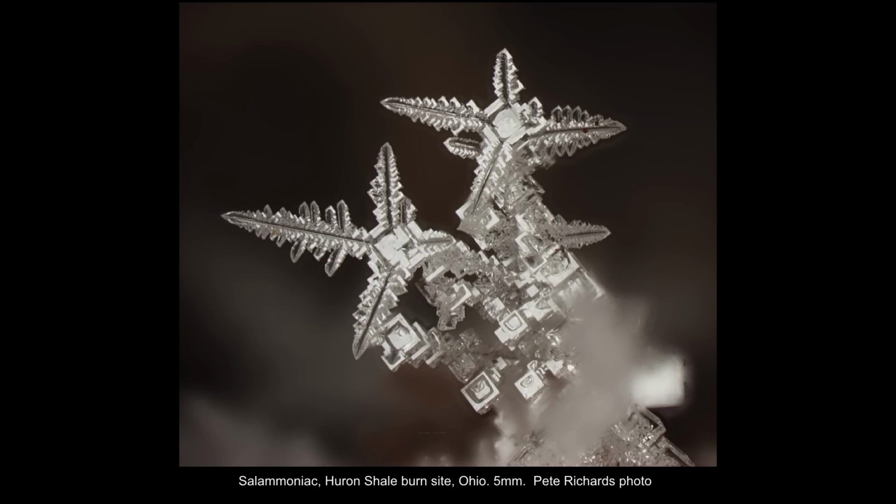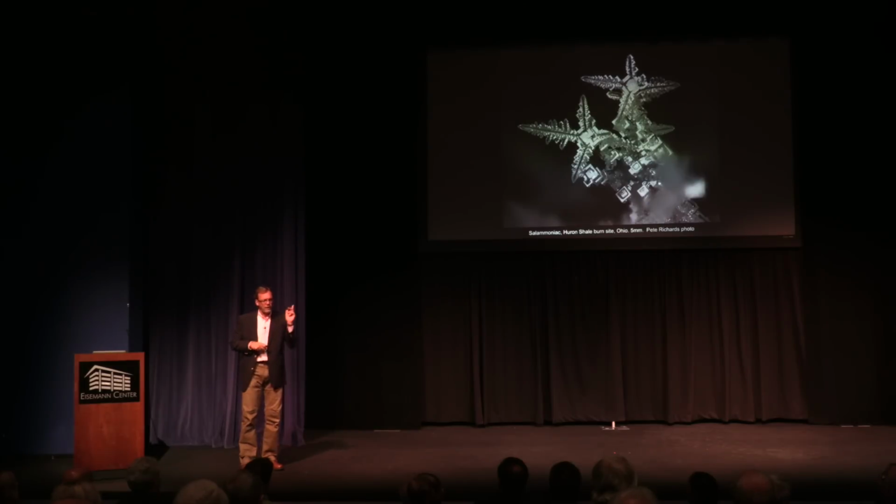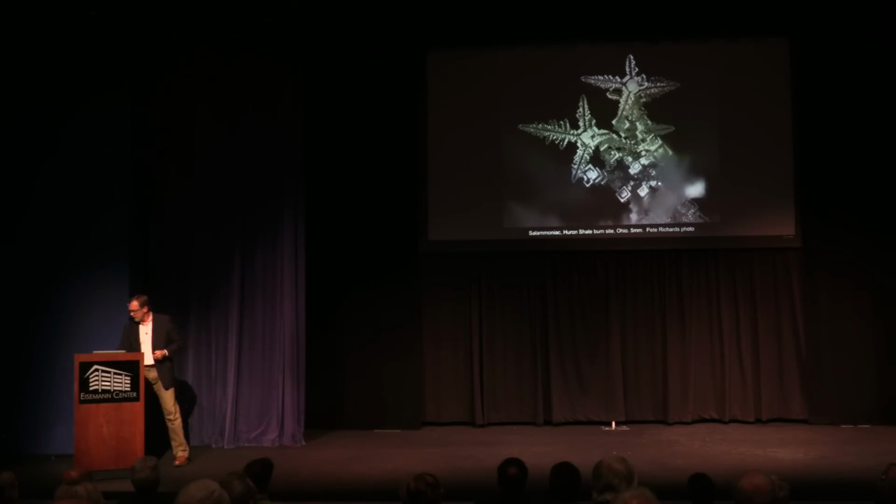And it's, from a crystallographic point of view, and what we're talking about today, just fabulous, because you can see these crystals down in here. What morphology would we call these? Hoppered. But the hoppered crystals near the edge here are starting to grow out preferentially at the corners, forming these dendrites. So we're right on that boundary between hoppered growth and dendritic growth on the Sunagawa diagram.